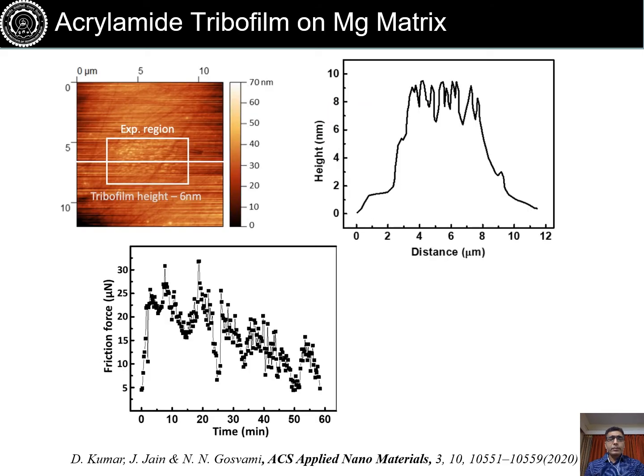So we took up this AFM based approach, and again looked at the purely magnesium matrix in an as cast alloy, and we can clearly see that a film has developed on the magnesium alloy matrix, which is much softer and was wearing in the case of ZDDP containing lubricant. But here we see acrylamide has formed a nice tribofilm. Of course, this tribofilm is only a few nanometers thick, much thinner than ZDDP films on the precipitate region. But with ZDDP, no film develops on the matrix.